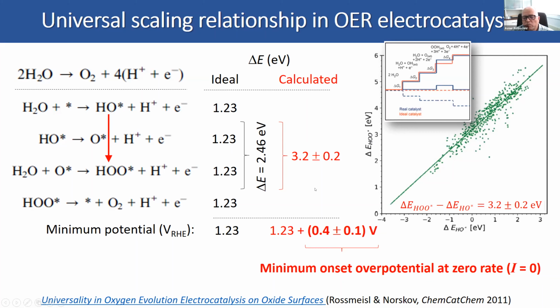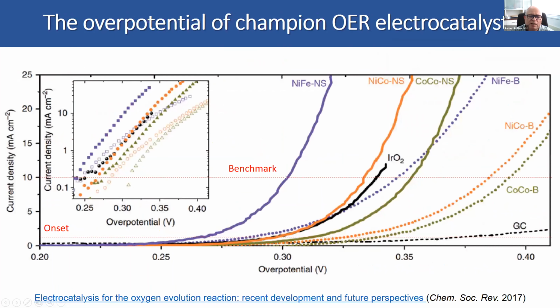That's not standard overpotential. It doesn't have to do with the kinetics of the reaction, but with thermodynamics of the reaction, because it's a multi-step reaction where different steps are not equal. And that is the main reason why we suffer from low efficiency in conventional electrolysis. And you can see that that's not only calculation, also the best electrolyzers, the best electrocatalytic material for oxygen evolution, they show that under a low current density, look, this is not high current density, that's 10 milliamps, you get an overpotential of 0.3 volts, which translates into this relatively low efficiency.